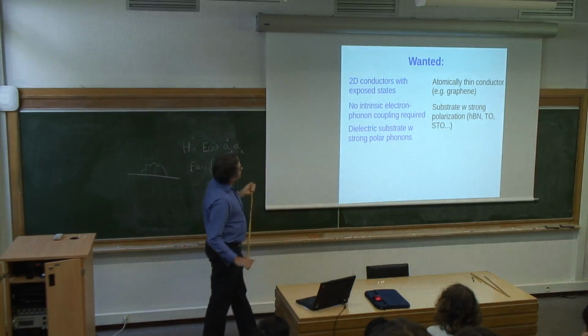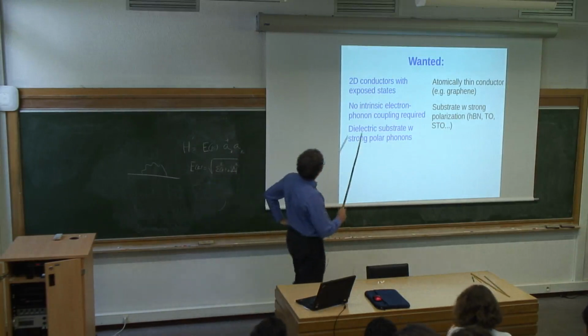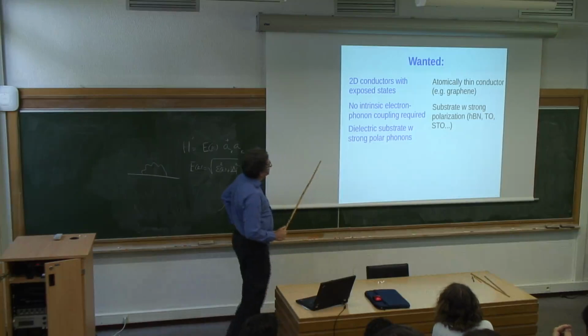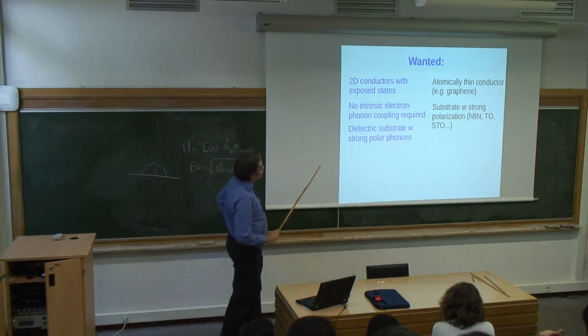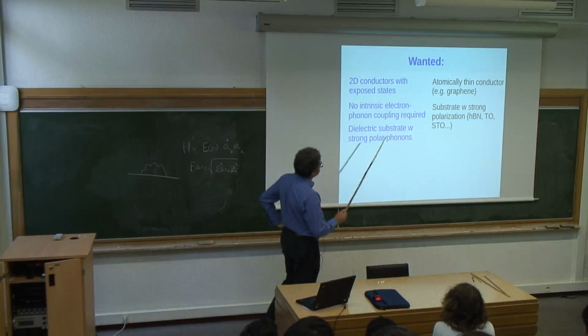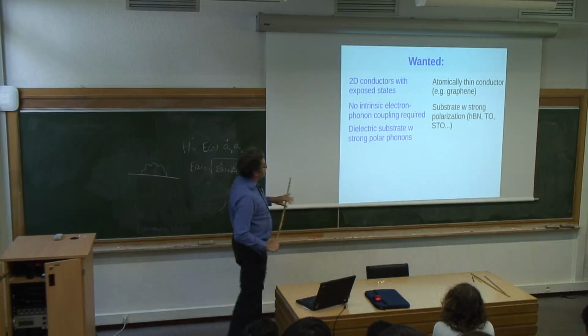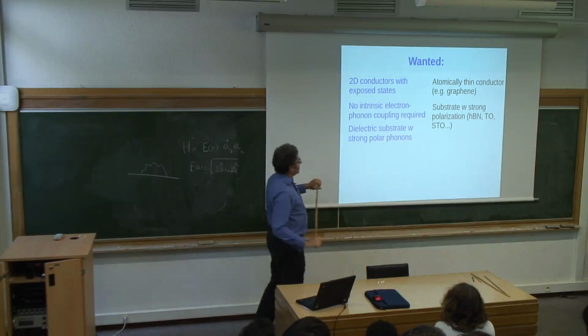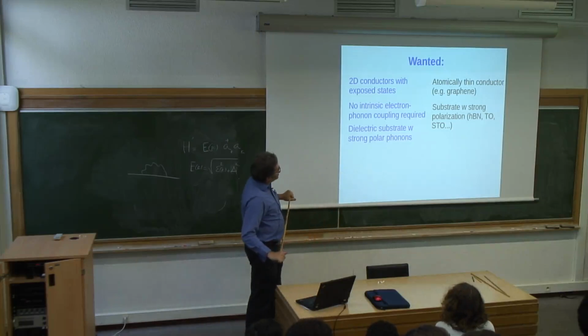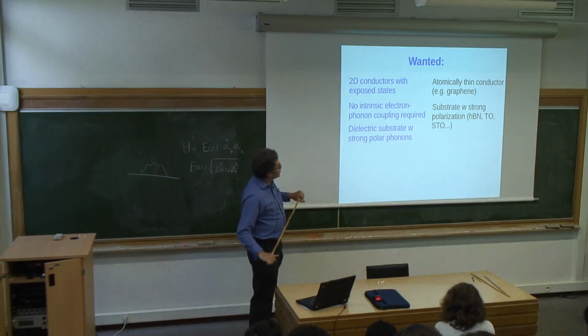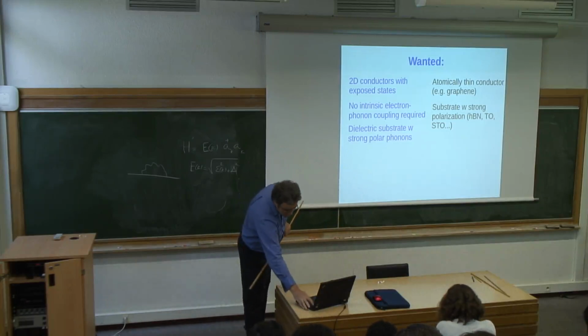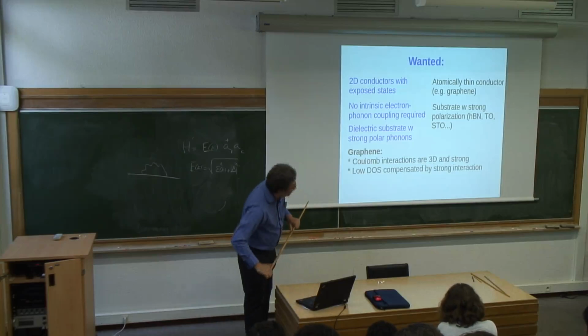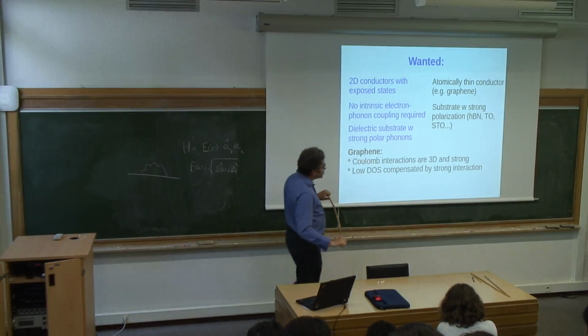So what we want is a two-dimensional conductor with fully exposed states, and we are not looking for one with strong electron-phonon interaction intrinsically, because we are going to put on a dielectric substrate with strong polar phonons. Graphene is obviously one candidate, but perhaps not the only one. More on that shortly. So graphene is good.